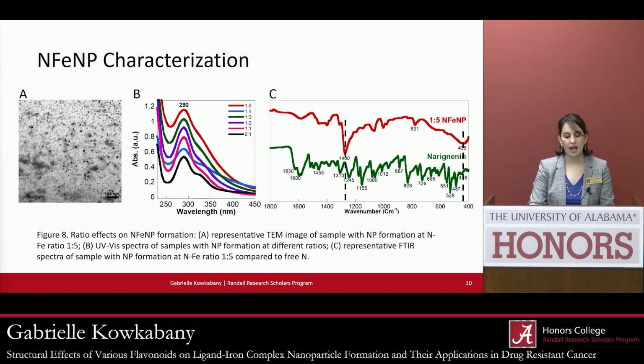And so you can see in part C of this figure, at the 1400 range, there's a big peak in the red line where that's the nanoparticle. And so that is demonstrating that there's iron coordination around the ketone group of naringenin. And then the peak around 435 is iron coordination with the hydroxy group at the top of the third ring